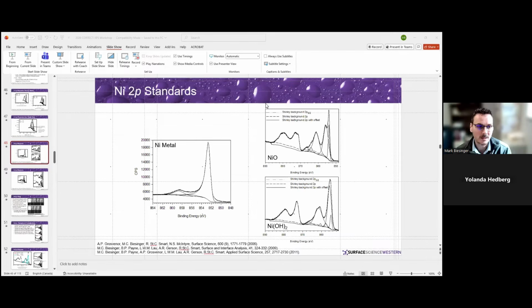And so they've developed, and it's on the website now, these new updated fitting parameters for FeO and a little bit for Fe3O4 and, I think, FeOOH that have improved the fitting, because they were able to get better standard spectra since they could clean the NiO samples or the other samples in situ using a gas cluster ion source that gave them a little bit better, purer spectra. And it did make a difference to allow you to get better quantification of these things. And so I'd have a look at those papers showing how those things work.